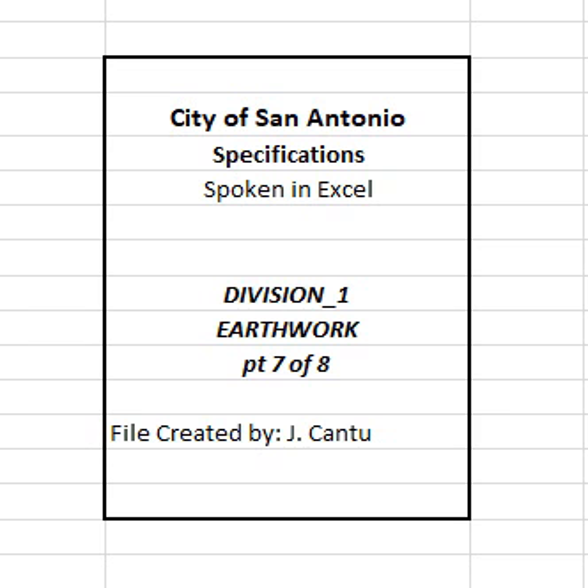C. Application of cement. Uniformly apply cement using slurry placement unless approved by the engineer. Add cement at the percentage determined in Section 201.2.E, Mix Design. Apply cement only on an area where mixing, compacting, and finishing can be completed during the same working day. Start cement application only when the air temperature is at least 35 degrees Fahrenheit and rising or is at least 40 degrees Fahrenheit. The temperature will be taken in the shade and away from artificial heat. Suspend application when the engineer determines that weather conditions are unsuitable.